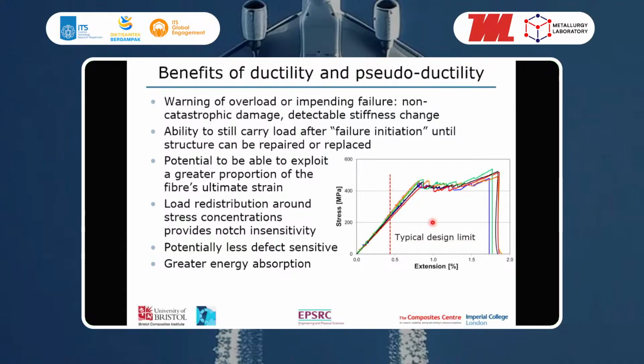So there are trade-offs. Unfortunately in this world you rarely get something for nothing. If you look at this stress-strain response, a carbon on its own would go to a higher stress than this, but it would fail catastrophically. So it all depends what you want. If you're after ultimate strength, then you're better off with carbon on its own. But if you want to make it more tolerant of damage and to have this gradual failure and not see a catastrophic failure, and to see more tolerance of notches, then this is a better response. We've looked at different applications.